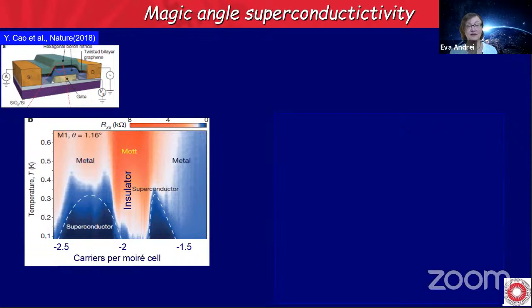But now if you look at this, the critical temperature of this superconducting dome is pathetic. It's less than a degree. It's 300 millikelvin. Why should anybody care about such small superconducting temperatures? I mean, we have much higher, up to 200 Kelvin. So what's the big deal?